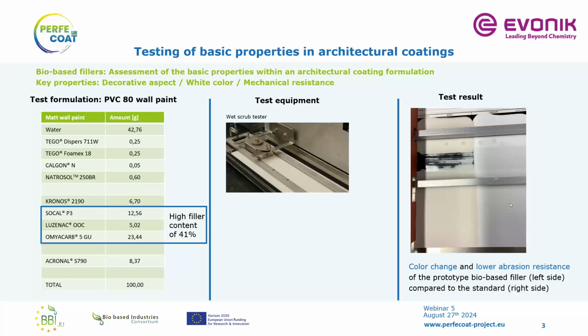And unfortunately, you can see already the substrate coming through, the black appearing is the substrate. That means that a part of the paint has been removed through the brushing, indicating that the mechanical resistance is on the weak side for the standard of the industry. But the film was looking good in terms of appearance, at least.